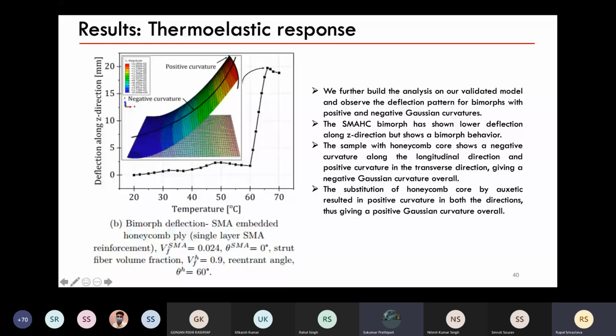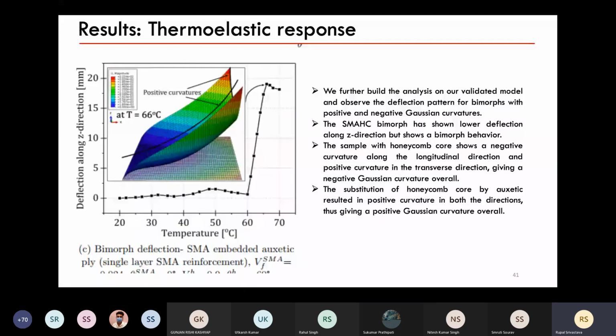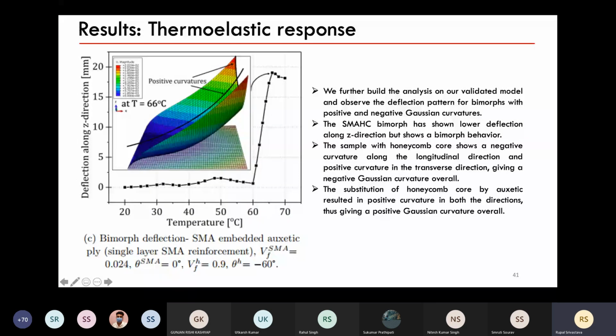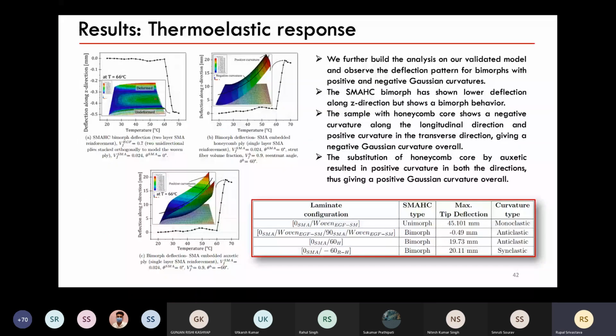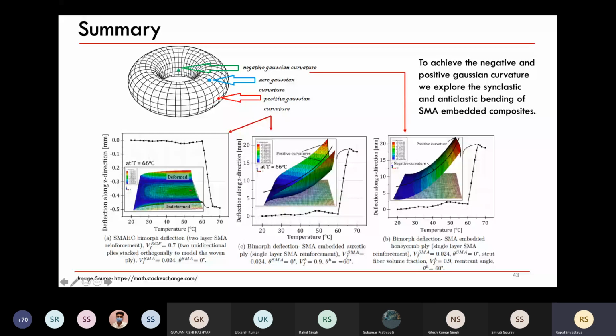Okay, and then the final one, in which I had that auxetic layer that I was talking about. One layer is of SMA inside, and another layer is auxetic. And in this, we are getting positive curvatures in both the directions. So this is also going positive, this is also going in the same direction. So we have a positive Gaussian curvature. And now you'll know why I'm emphasizing zero Gaussian curvature, negative Gaussian curvature, and positive Gaussian curvature. It's because our torus structure is made up of three different curvatures. So if we want to get that torus shape that I was talking about for the inflatable structure in space, the inflatable antenna experiment, we need a torus structure. And for that torus structure, we need three different Gaussian curvatures. One is negative, one is zero, and one is positive Gaussian curvature. The zero one is very simple.